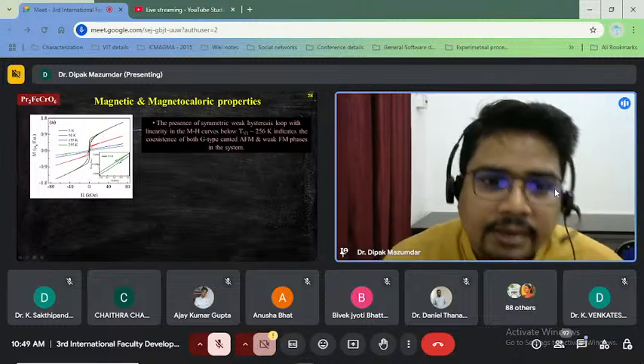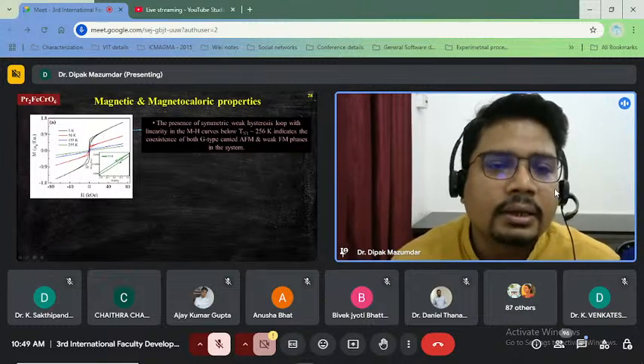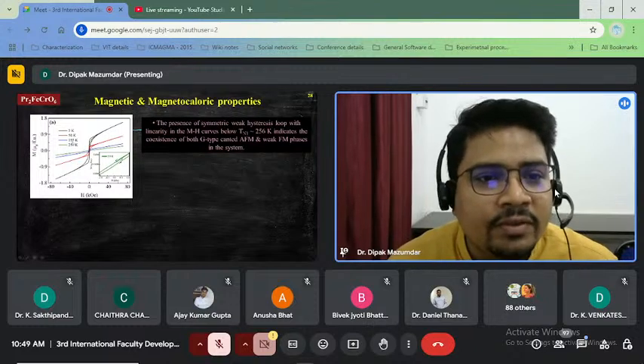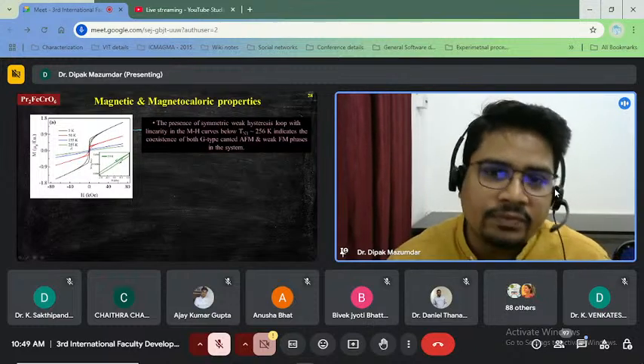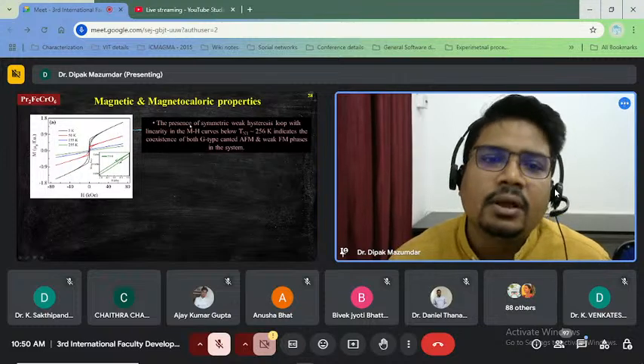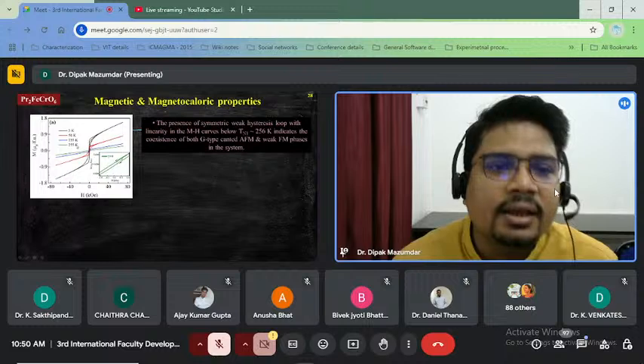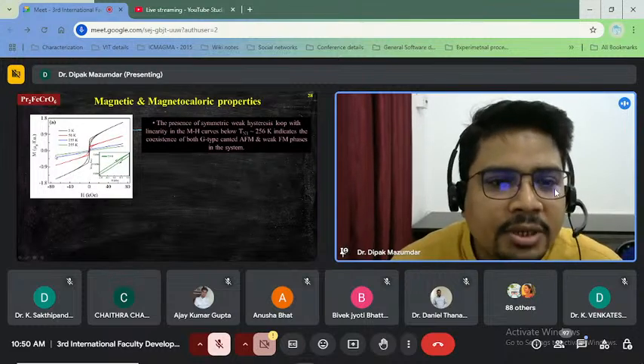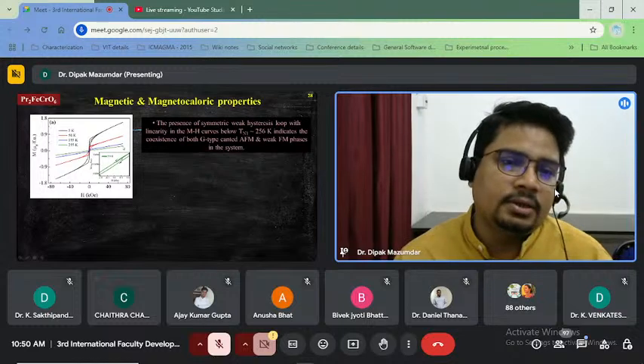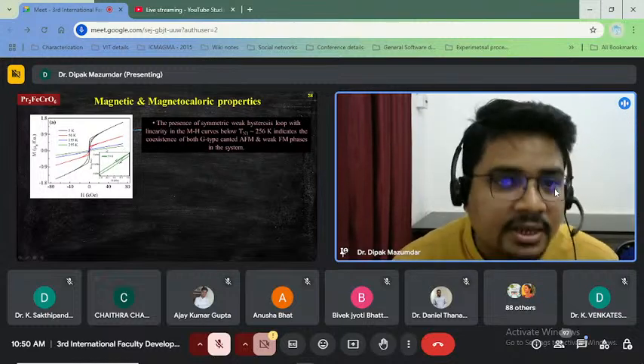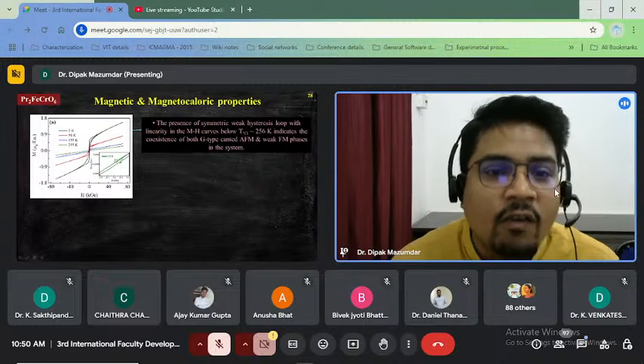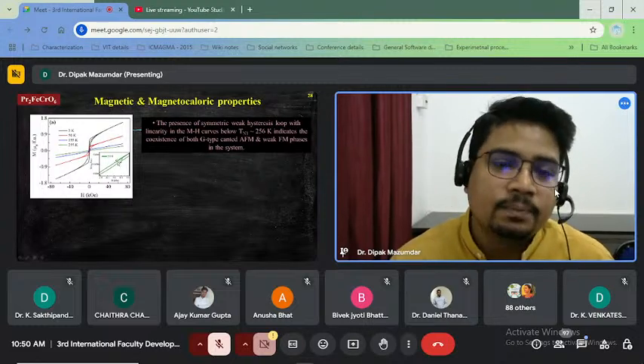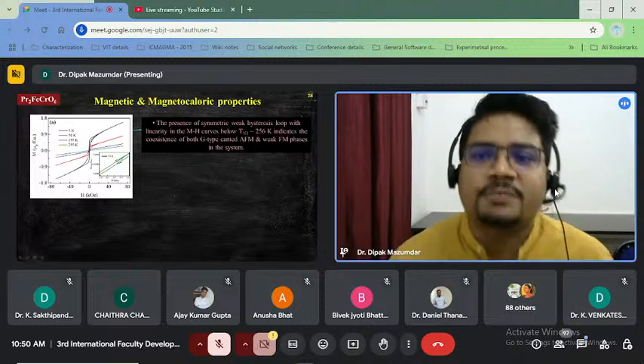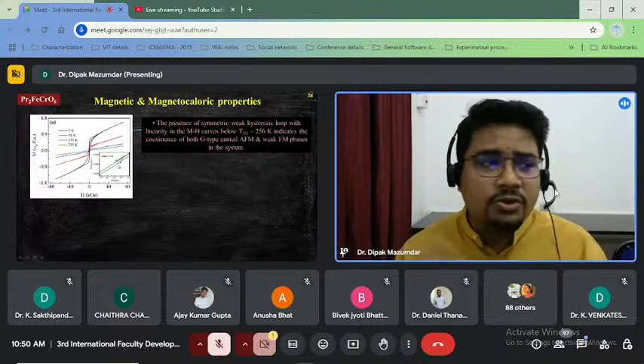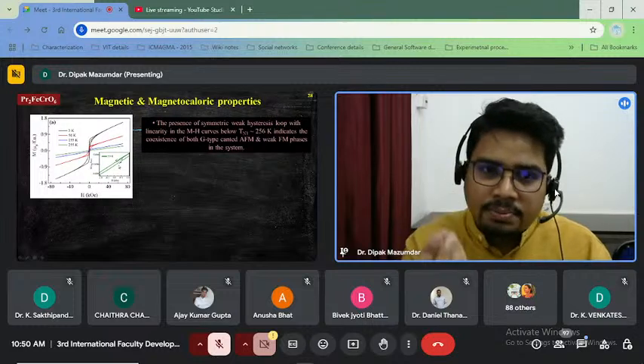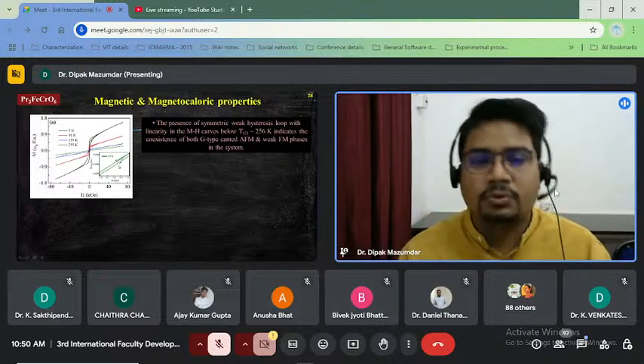And this weak ferromagnetic phase has been observed here. Here and above, you can see in this data 255 Kelvin, our transition TN1 is around 256 Kelvin. So when we take the data around 255 Kelvin, this should be a straight line, but we did not observe that. We did not see any overlapping of field cooling and field heating data. There is a field hysteresis present in that loop. So it also indicates that there is a presence of weak ferromagnetic phase in this compound.